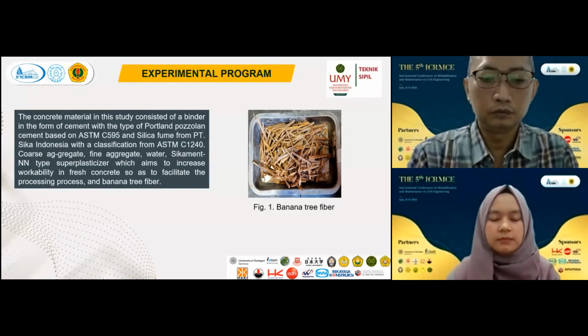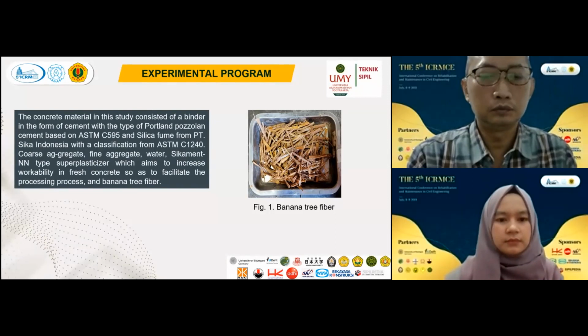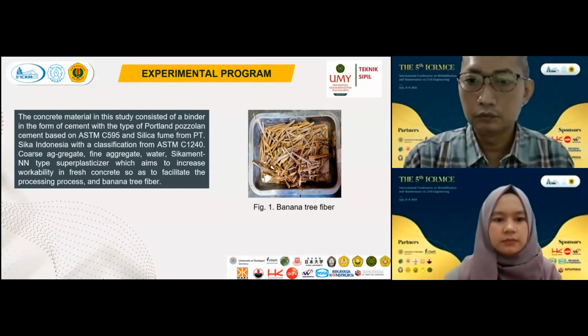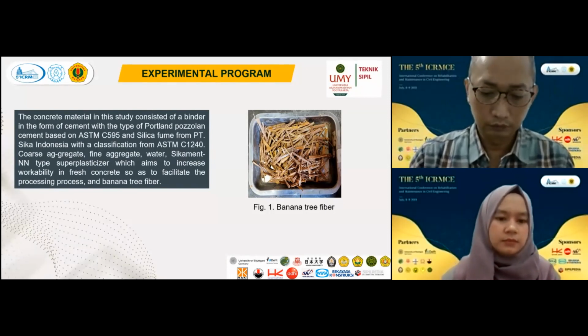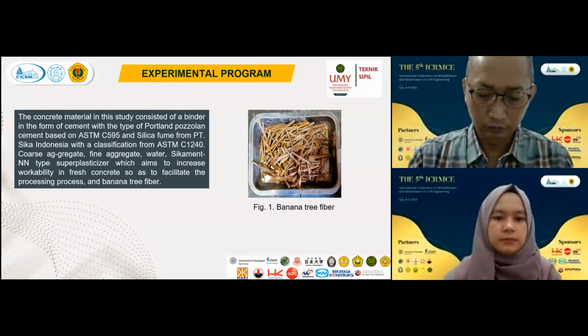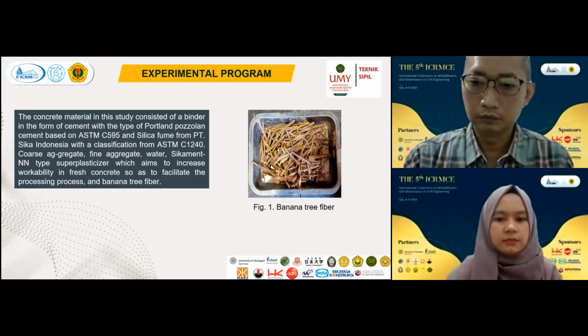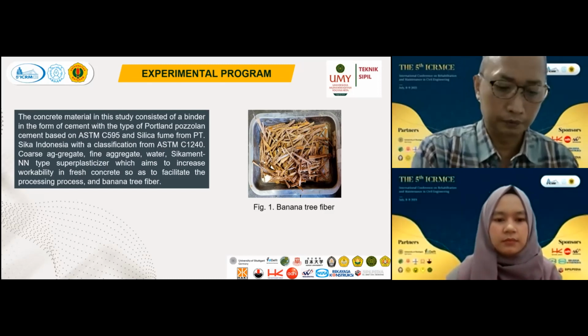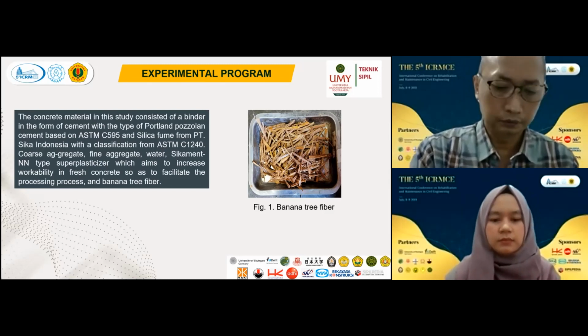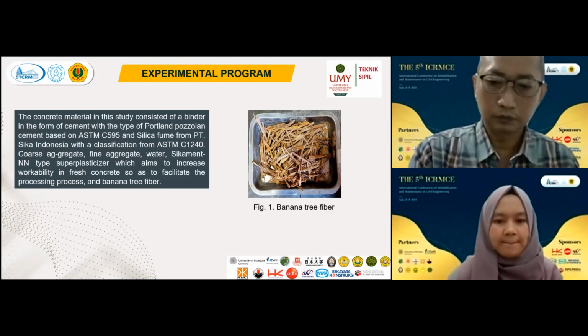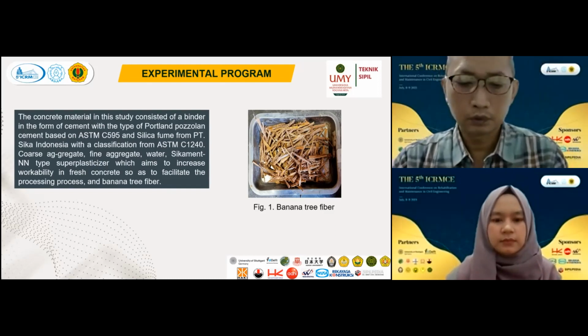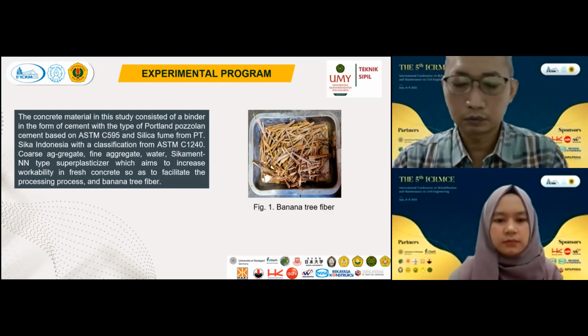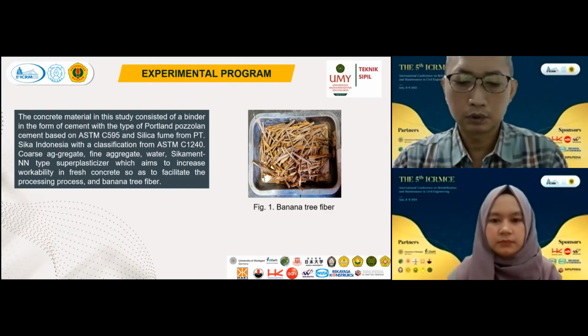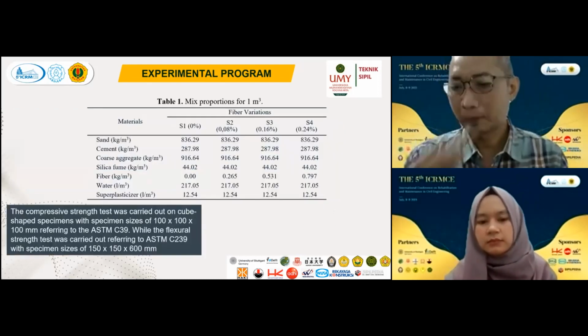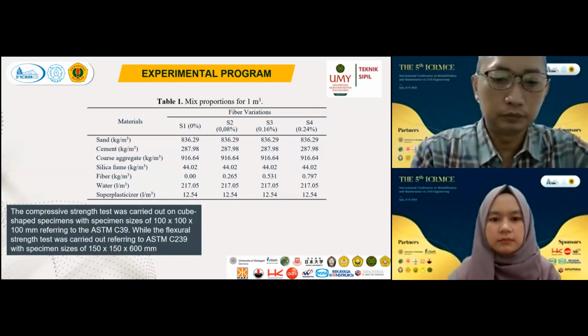And this is an experimental program. The concrete material in this study consists of a binder in the form of cement with the type of Portland pozzolan cement based on ASTM C595 and silica fume from PT Sika Indonesia with a classification from ASTM C1240, coarse aggregate, fine aggregate, water, and Sikament-NN type superplasticizer, which aims to increase workability in fresh concrete so as to facilitate the processing process, and banana tree fiber. And this is the figure of banana tree fiber. This is a mixed proportion for 1 cubic meter of concrete.